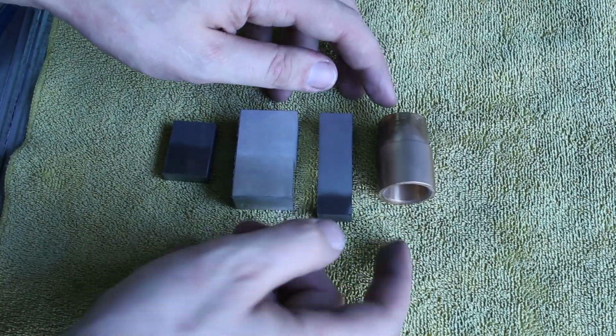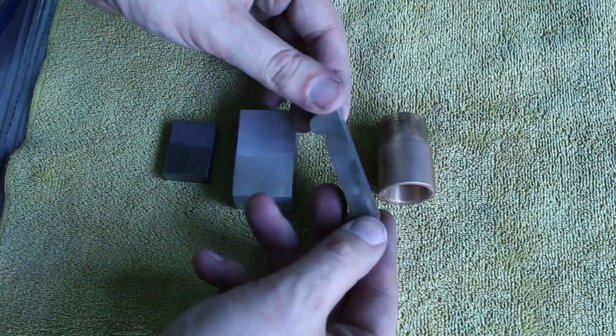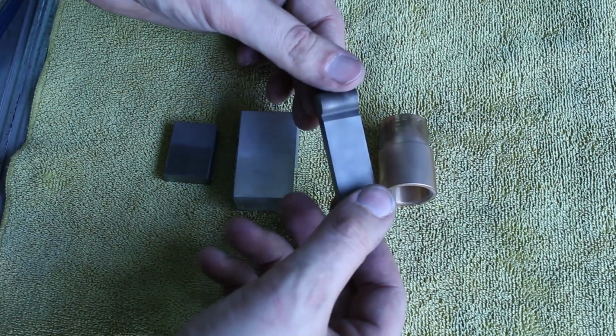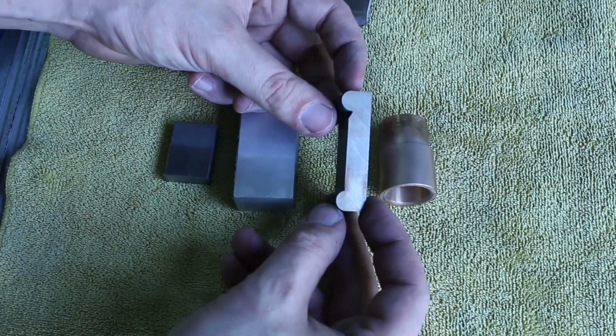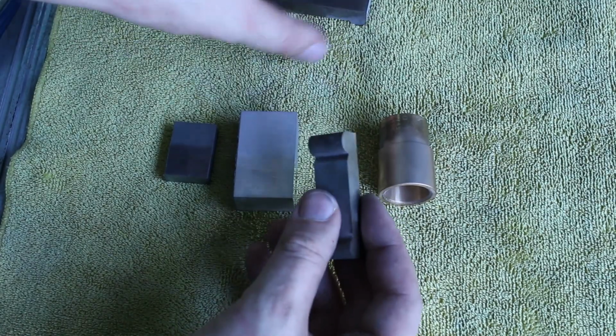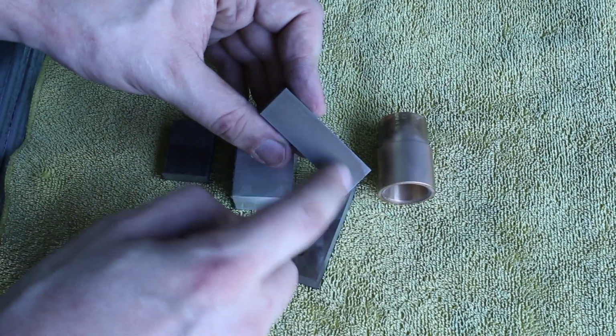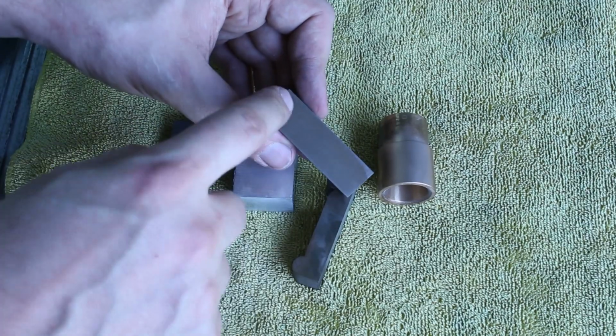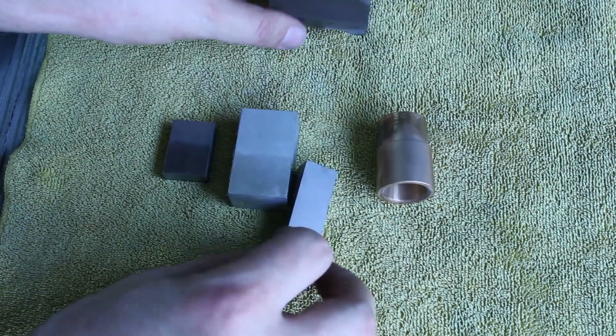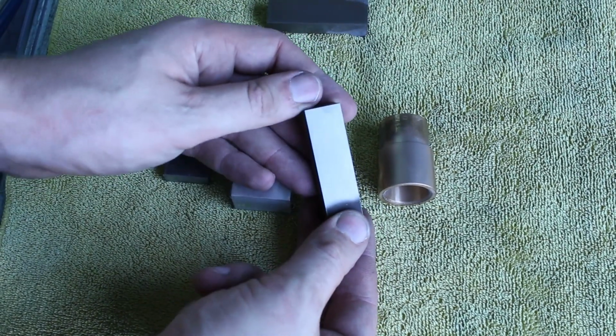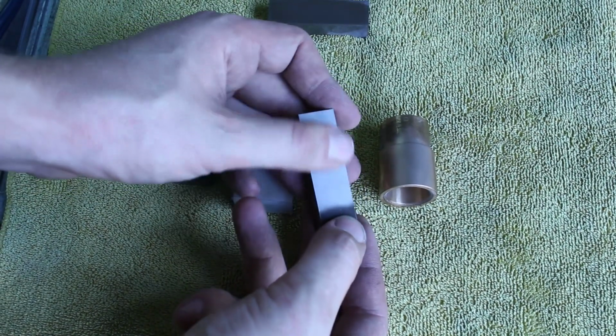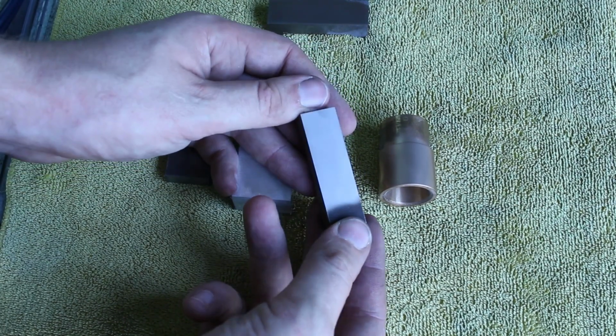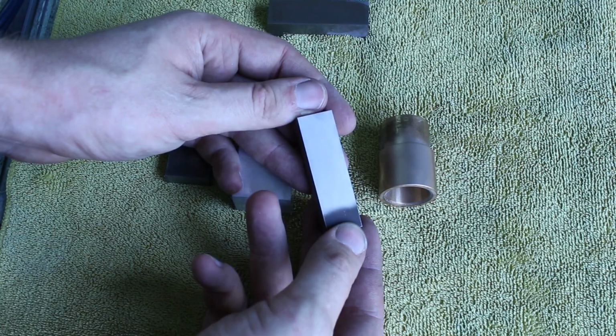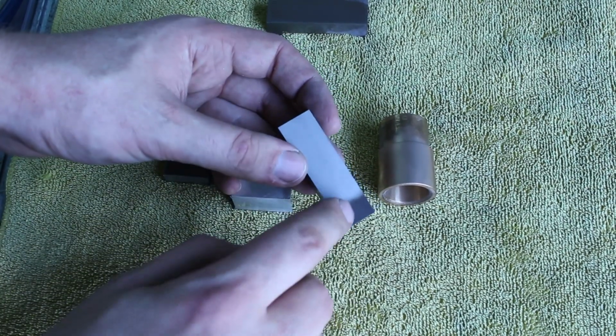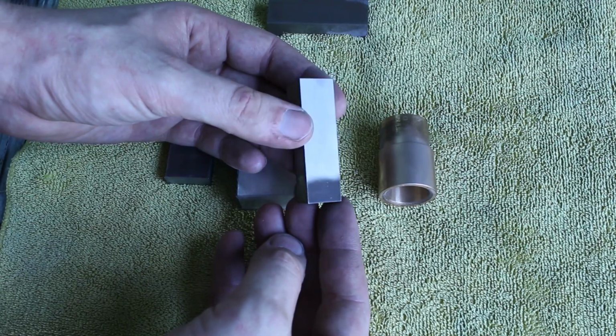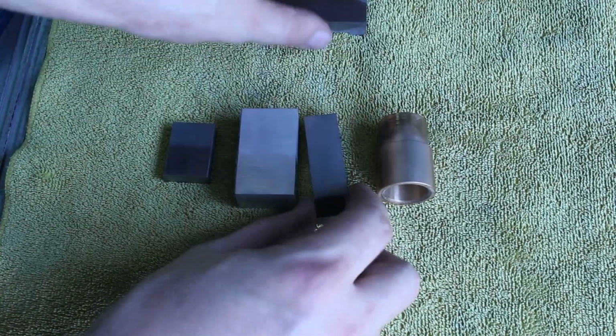Here are the examples I just showed in the cabinet. Let's start here. This is a piece of high-speed steel that has been wire cut into the shape of a small sine bar. The surface finish starts something like this, the EDM recast skin. It's very rough and it doesn't look very nice. And after blasting it with the aluminum oxide, glass bead mix, it's a really nice finish. On each of the examples I left a little bit of the original surface next to a blasted surface.